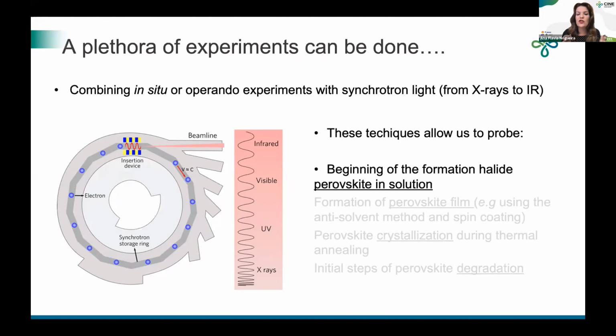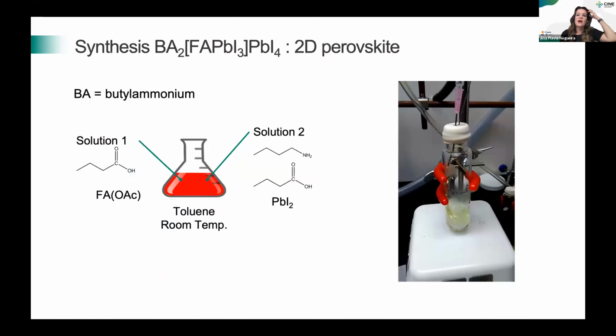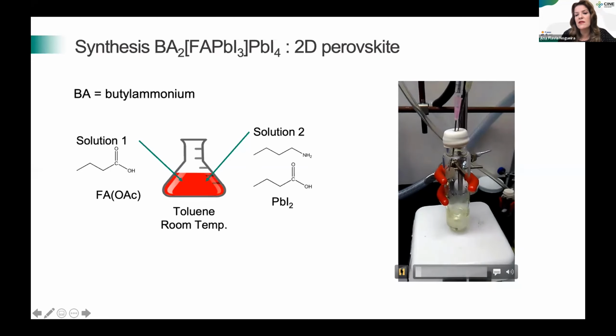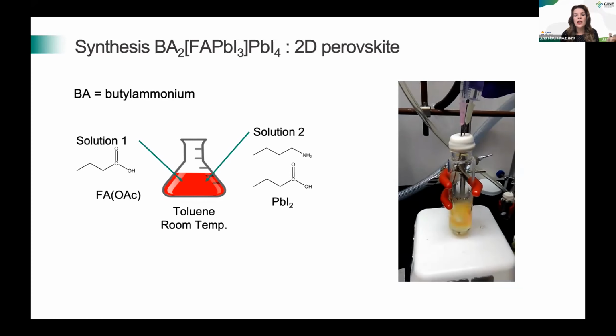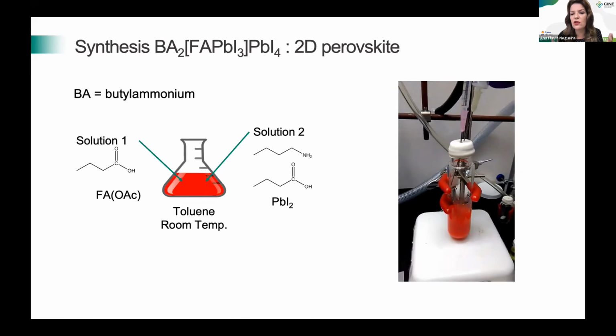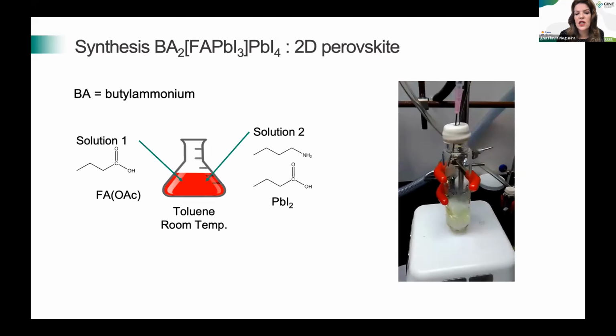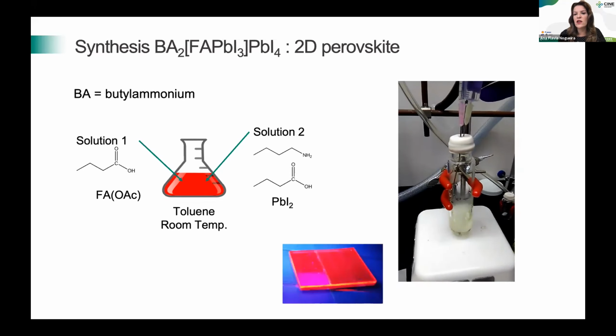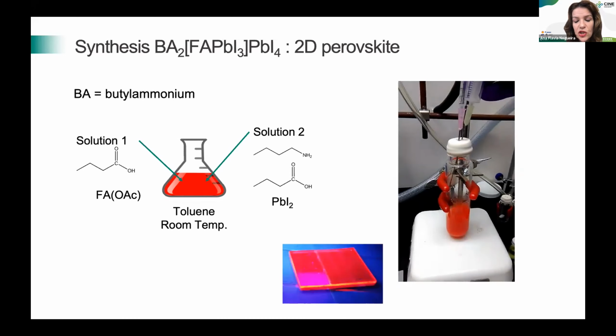So starting with tracking the formation of these perovskites in solution. This is the synthesis of a 2D perovskite, where the cation is a long cation, which is a butylammonium cation, and this is our organic cation. This is a very simple reaction that we developed in our lab, where you can make this very nice film at room temperature. I think I can play the video here, you can see. You can just mix these 2 solutions of precursors and you have this 2D material. It's a really fast reaction. These films are really bright, very interesting for light emitting applications.